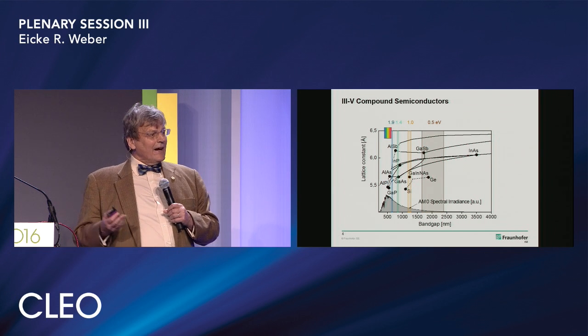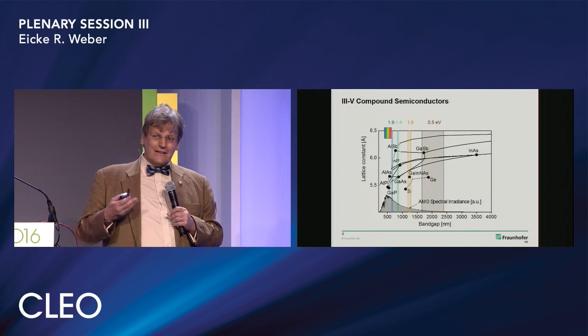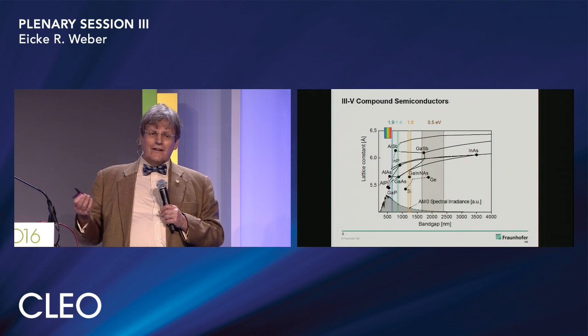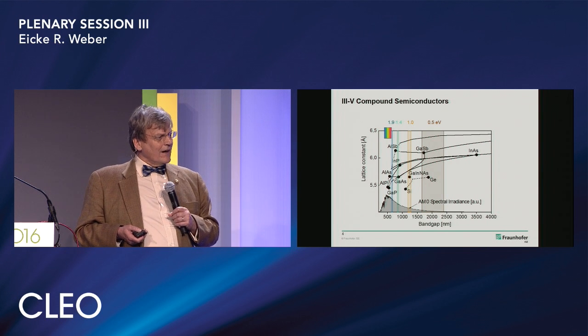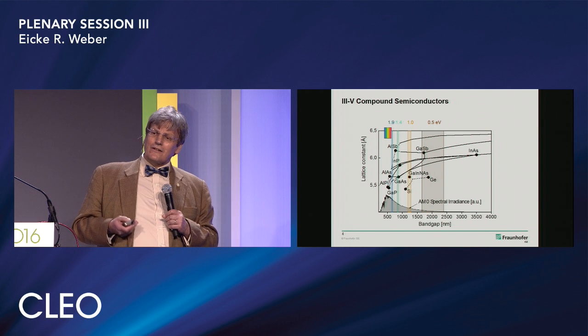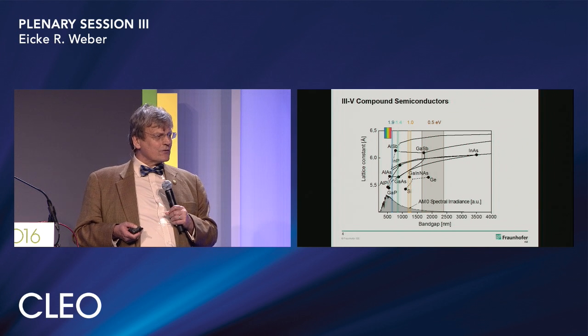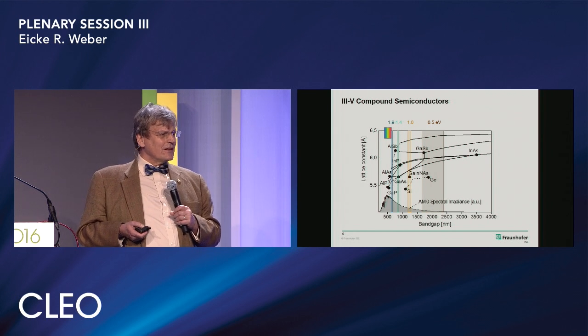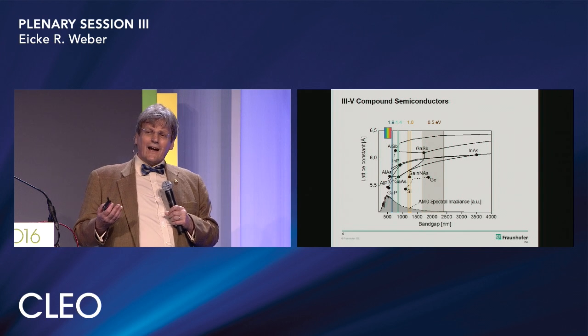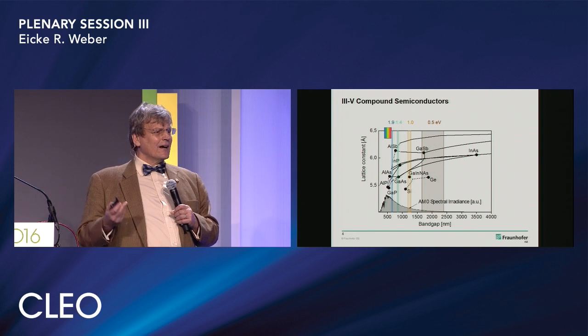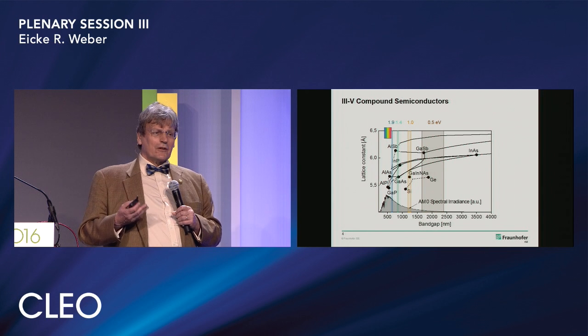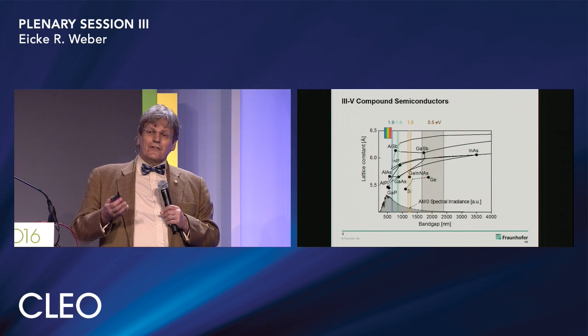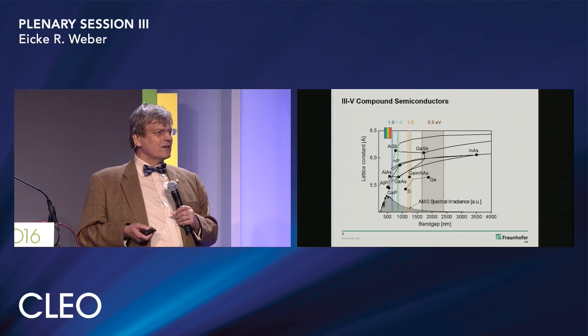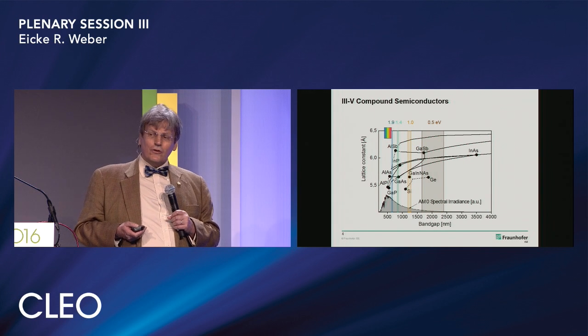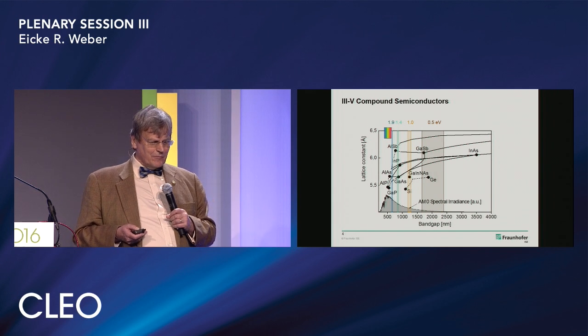And therefore, any problems with defects, interfacial defects, everything that can enhance recombination and increase the surface recombination velocity is very detrimental. And therefore, photovoltaics is one of the most exciting areas of materials research because it's so incredibly demanding to make really minority carrier devices which are coming close to theoretical efficiency limits.